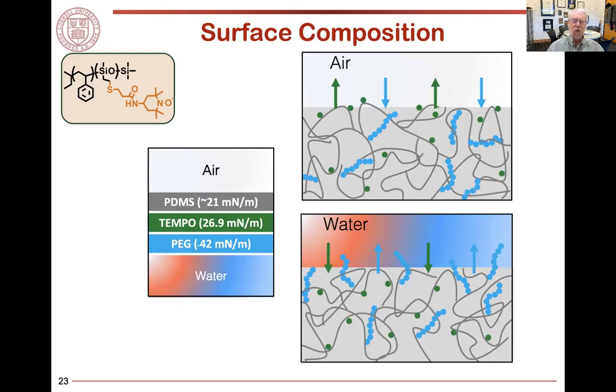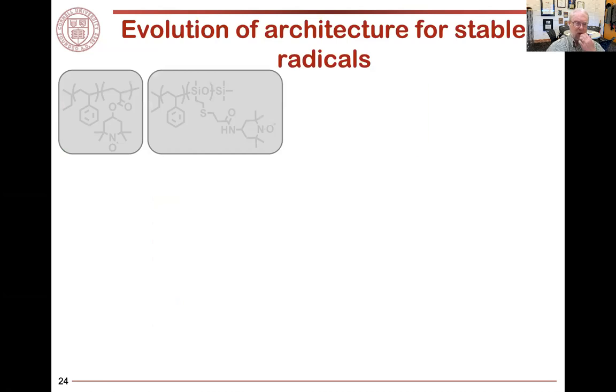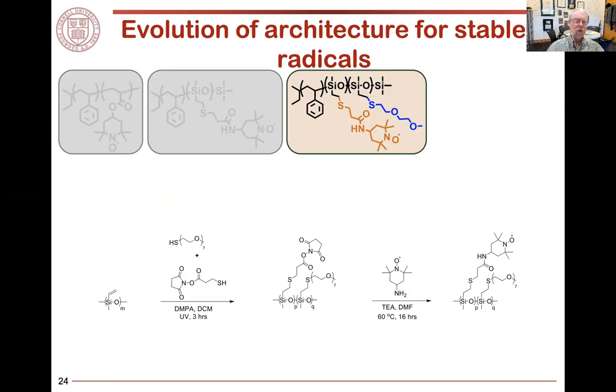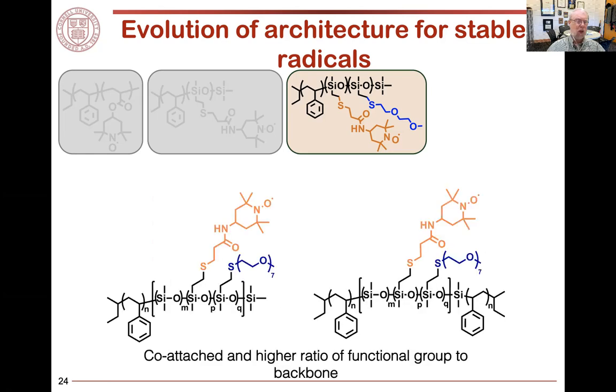And what we need to do is to avoid the situation where the TEMPO is buried by the PDMS when we coat it in air, and the TEMPO is buried by the PEG when we expose it to water. So ultimately we had to do the harder synthesis that we were clearly trying to avoid and incorporate both PEG and TEMPO on the same PDMS backbone. Clearly we have the same thiol-ene click chemistry that we can use, and we employed it. And we can also make both the diblock and the triblock copolymer. So we can vary the ratios, we can control overall composition. And again, the styrene acts as an anchor block or anchor segment in our multi-layer structure.